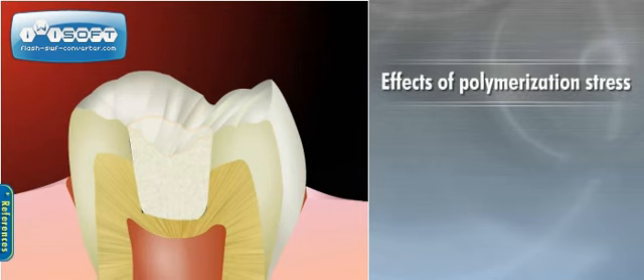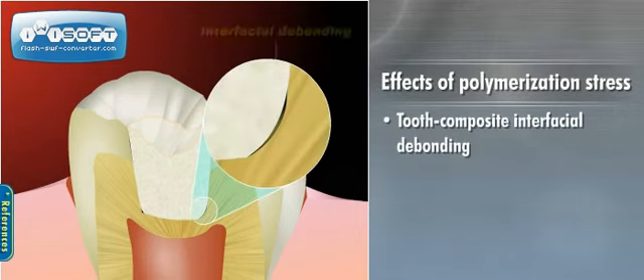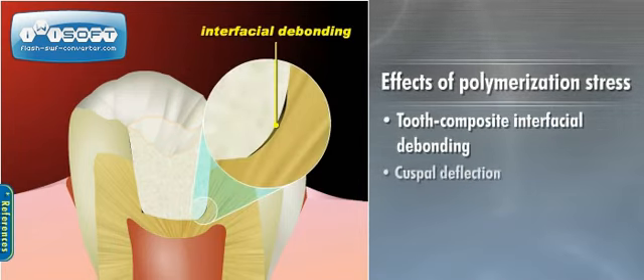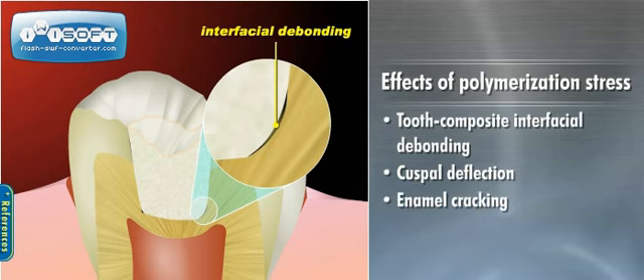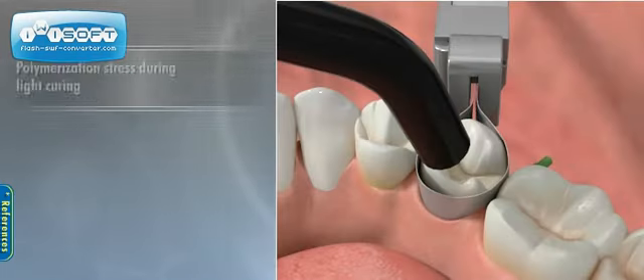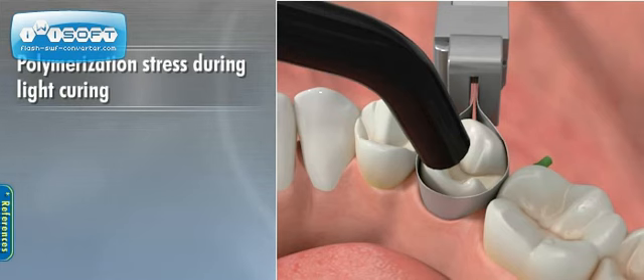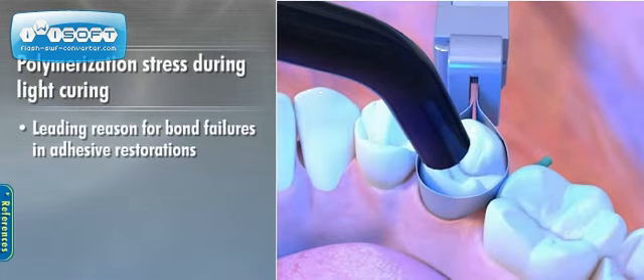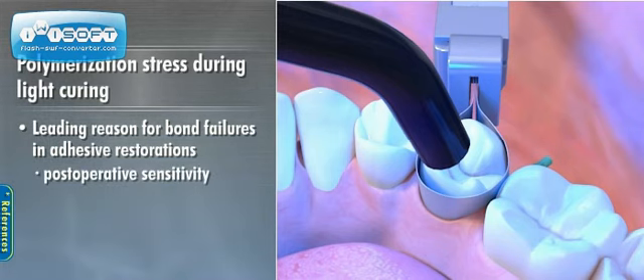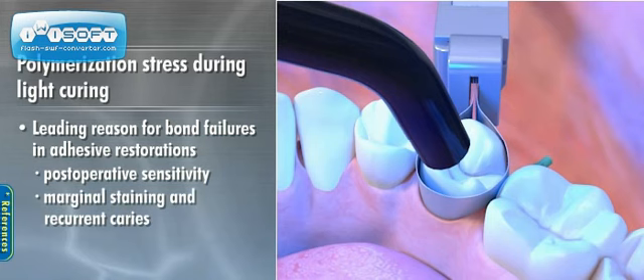The effects of this stress, such as tooth composite interfacial debonding, cuspal deflection, and enamel cracking, are frequently implicated as primary reasons for the failure of posterior restorations. In addition, the polymerization stress produced by dental composite materials during light curing is a leading reason for bond failures in adhesive restorations, resulting in postoperative sensitivity, marginal staining, and recurrent caries.